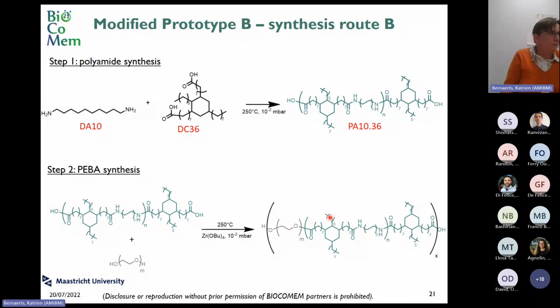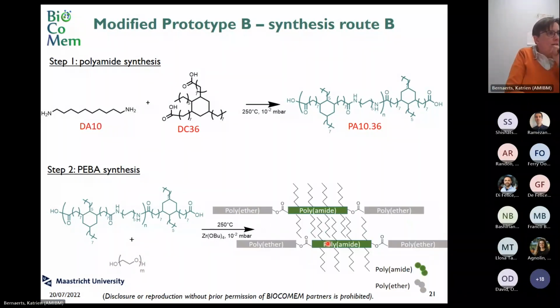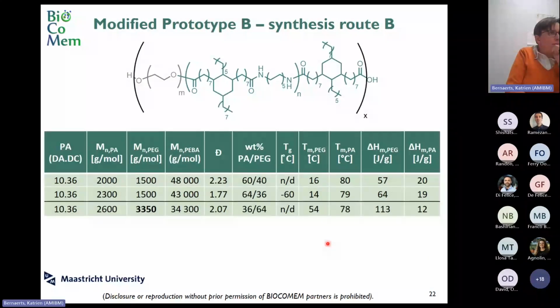The composition stays similar, but now instead of using the fatty acid diamine, we use the diacid functionalized fatty acid, and instead of using a small molecule diacid, we use a diamine. So this results then in the acid functionalized polyamide that is again combined with polyethylene oxide to give the PEBA. And the polymers we obtain, first of all, have pretty good molecular weights. And the melting point of the polyamide is around 80 degrees.